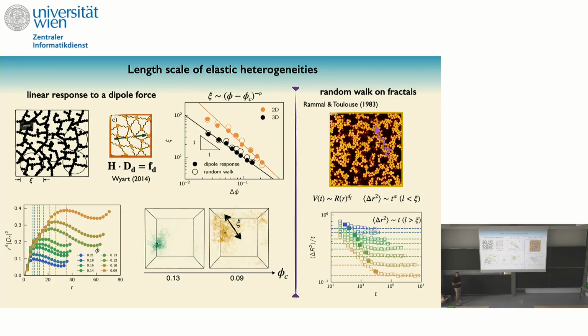This is because of the heterogeneity. This is because your system is not homogeneous enough to recover linear elasticity. In some sense, below this length scale, linear elasticity breaks down. You can't use linear elasticity. And above this length scale, you can envision your system as a homogeneous system. So again, this is something that you can do experimentally pretty fast if you have the images.